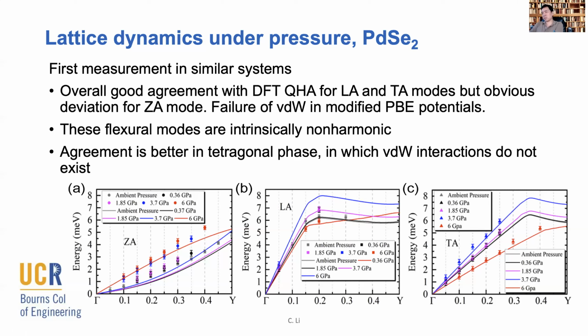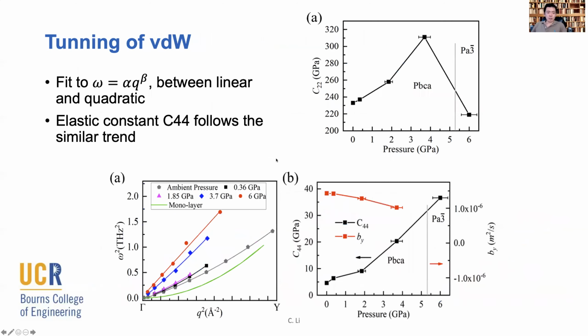And this agreement generally is better for the tetragonal phase, which is a higher pressure phase. And in this case, we no longer have van der Waals interactions between the layers. So we try to extract more information by fitting the acoustic phonons. And here we are enlarging the acoustic phonon measurement along this gamma-Y direction.